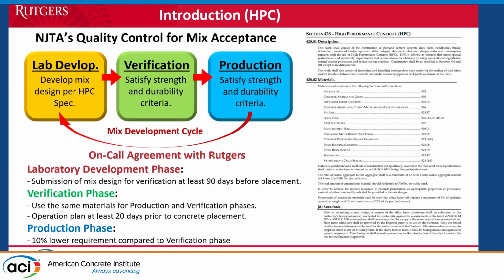And part of the process that we have followed, even for high-performance concrete, is to do the laboratory work, then invite about 3 concrete producers and the plant conditions, try to reproduce those mixes, get the experience, and then try to do a demo in the field under field conditions by either pouring it from a chute of the truck or from a pump. So the mix was designed for all these processes, and that's why it had to be very practical. So we developed many mixes, but the majority of them had some shortcomings when it came to implementing them in the field.